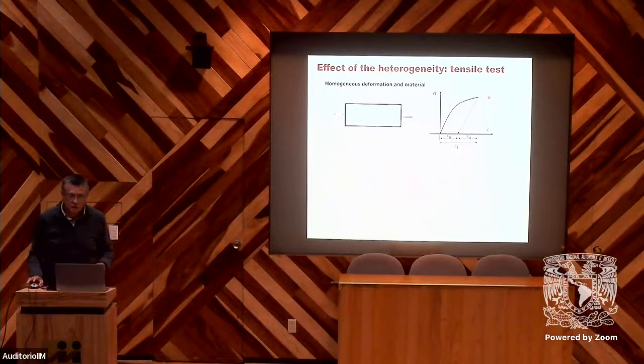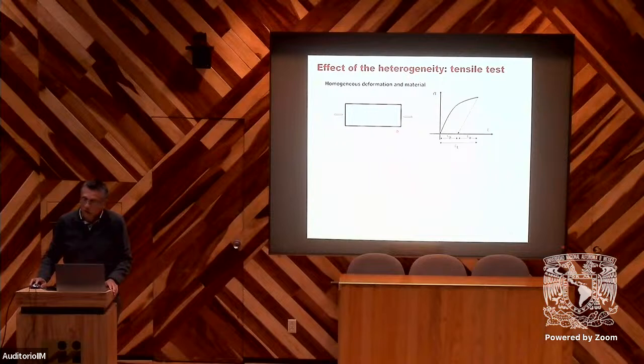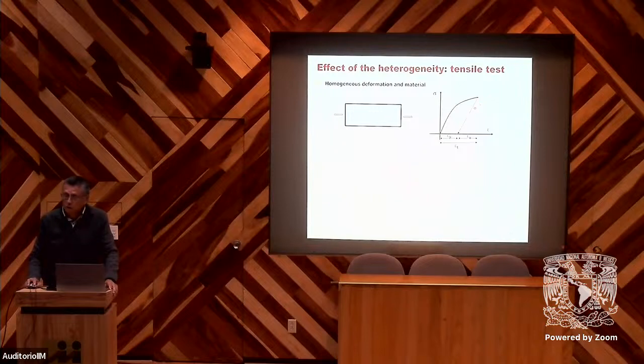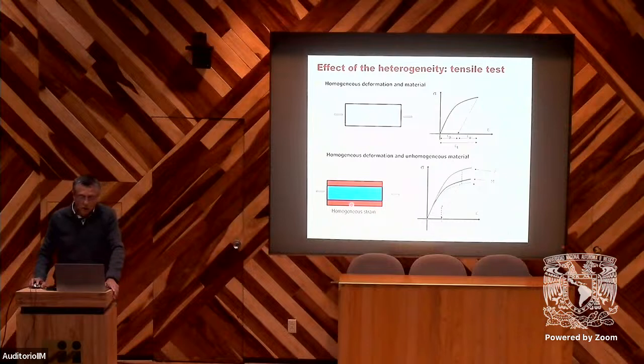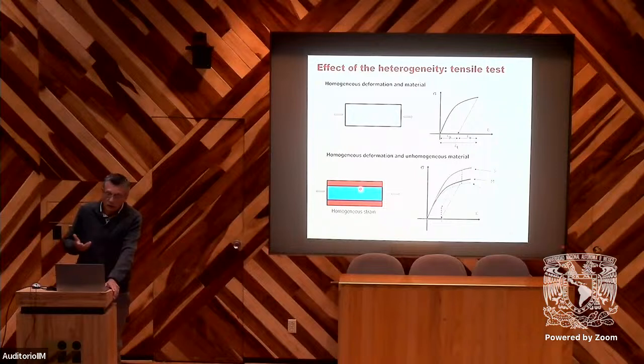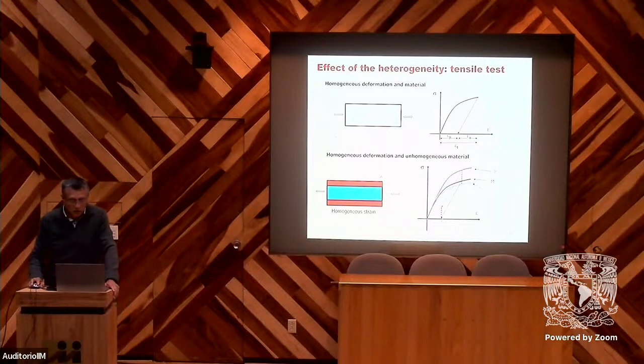In the case of the tensile test, if we make a tensile test and we unload after plastic deformation, we don't have any residual stresses. But if we make the same test, but with materials containing some heterogeneities, for example, if you consider a part after grinding, we can have a hardening of the near surface. So if we consider the surface layer and the bulk of the material, we have different behavior in tensile test. The surface will be harder than the bulk of the material.